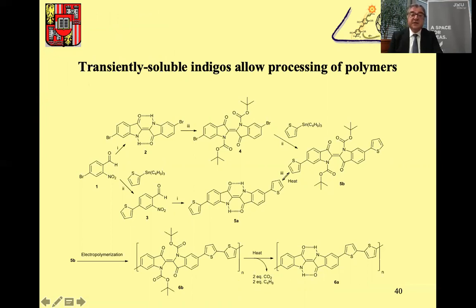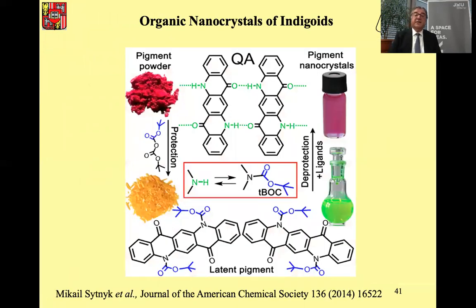So this is transiently soluble indigos for processing. And last but not least, you can make beautiful pigment nanocrystals out of these materials using that trick. As many of you know, this nanocrystal synthesis by hot injection method can be used now here. And if you inject this tBOC latent pigment into a hot bath, it will basically lose this tBOC group and fall back, and you can stabilize these kind of systems.